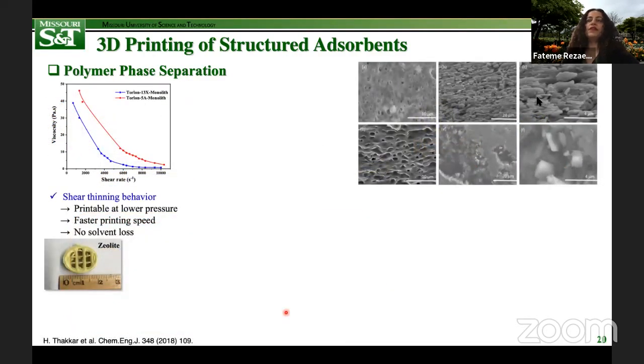A key factor in successfully printing a viscous liquid is to control the flow of the paste during extrusion, which is achieved by controlling its viscosity. Rheological properties of polymer sorbent paste dictate sorbent loading. The viscosity of the paste should be sufficiently high to avoid the collapse of the structure. This is what we expect, and also to mitigate the spreading effect of liquid paste, with well-controlled deposition during and after extrusion.